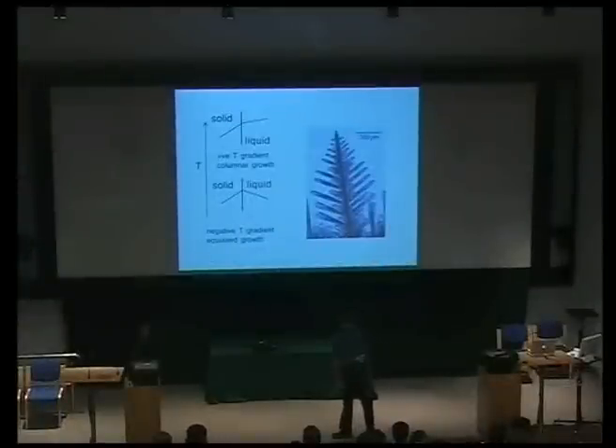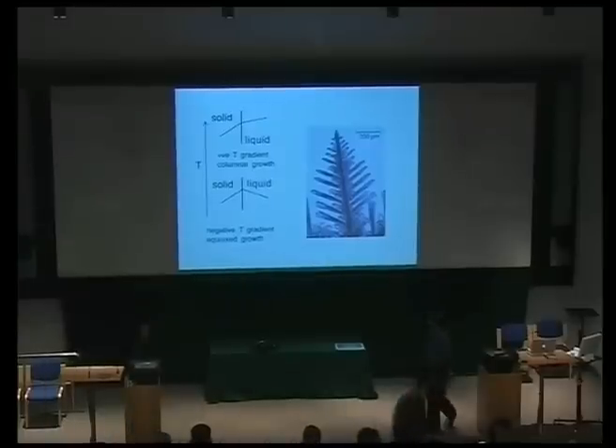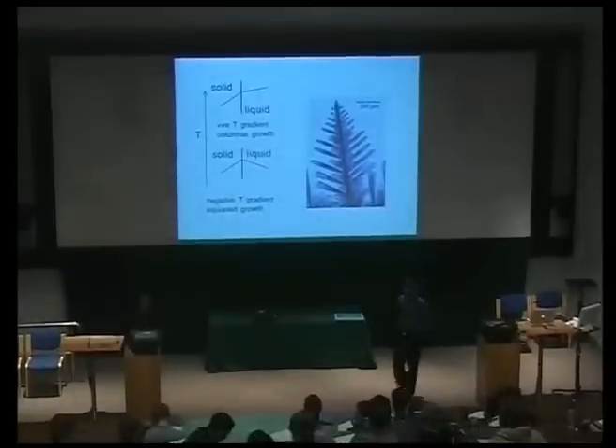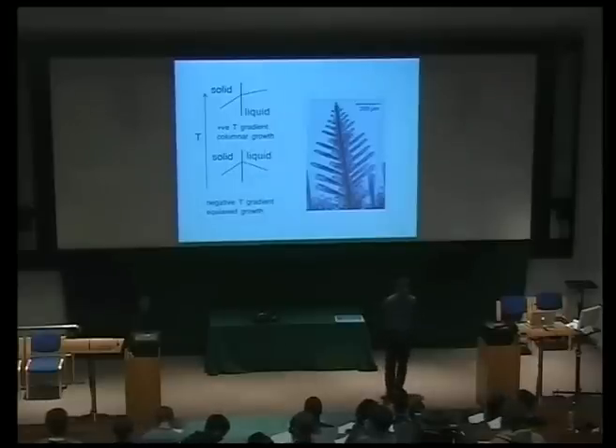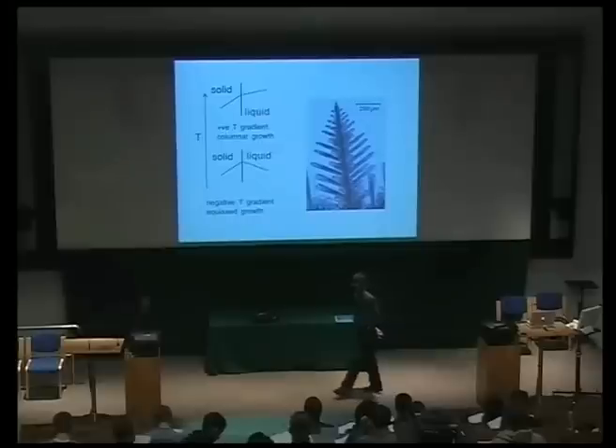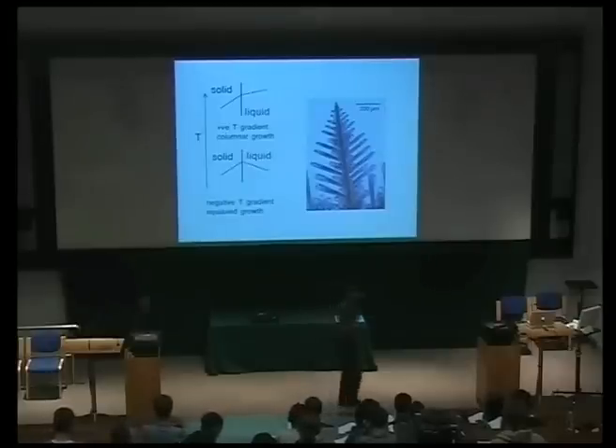In the next lecture we talked about the formation of dendrites and we covered pure materials, so there were no solutes involved in the solidification process. The only thing that limits solidification is the flow of heat. If you have a negative temperature gradient in the liquid — meaning the liquid is supercooled ahead of the transformation interface — then any small perturbation in the interface will tend to become unstable and develop into dendrites.